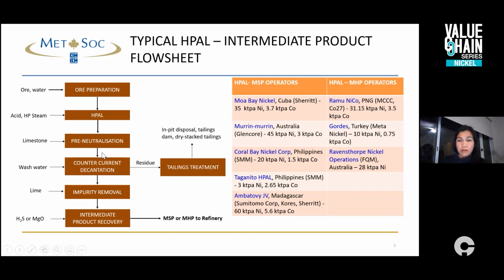That free acid, after it's flashed into atmospheric condition, is neutralized using limestone. And then whatever nickel and cobalt values are entrained within the slurry are washed with wash water in the counter current decantation. And the pregnant liquor solution then undergoes impurity removal, where the majority of the impurities like aluminum and iron are removed with the addition of lime. So it's a pH control impurity removal.